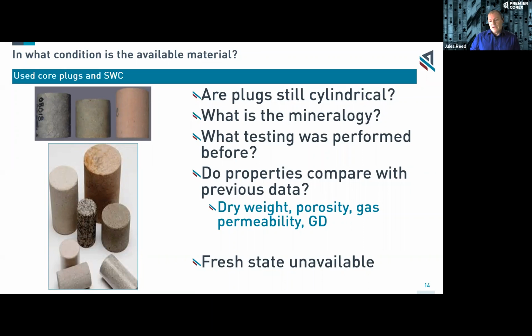consider those properties again. So measure the properties, look at things like the dry weight. Is the dry weight the same, or the grain density equivalent to the previous data? The porosity and the gas permeability. Now, these are being performed on samples where these measurements have been performed before, and so we should have a direct comparison, and they should be equal within standard measurement error.